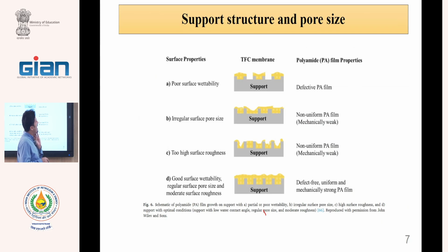But when we have a poor surface wettability, that means the MPD cannot diffuse in the membrane pores and cannot fill all of the pores. If we have a poor surface wettability, all of the pores will not be filled with the MPD, and therefore we have a non-uniform coating. Therefore, in this case, the chemistry of the support is important. We must use hydrophilic supports that can absorb the water, and MPD is in the water.